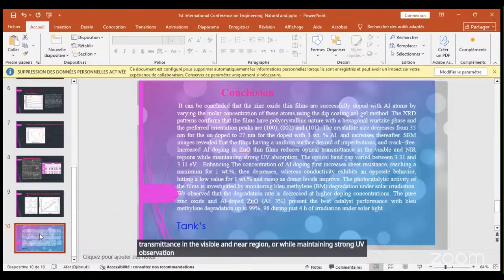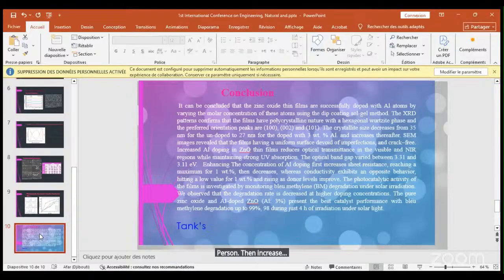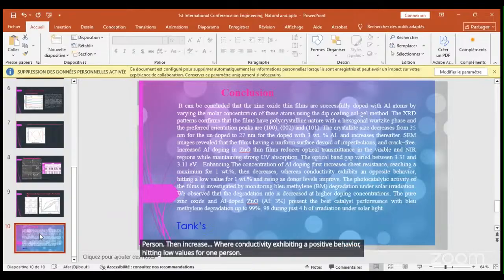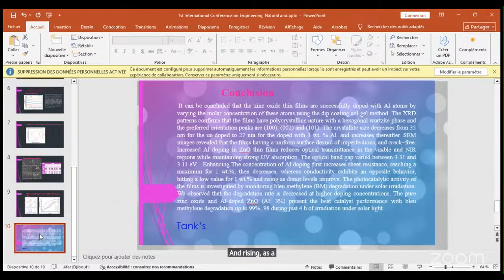The optical band gap varies between 3.31 and 3.11 electron volts with increasing aluminum doping concentration. First, sheet resistance increases and reaches a maximum for 1%, then decreases. Electrical conductivity exhibits an opposite behavior, hitting low values for 1%, and rising as the donor level improves.